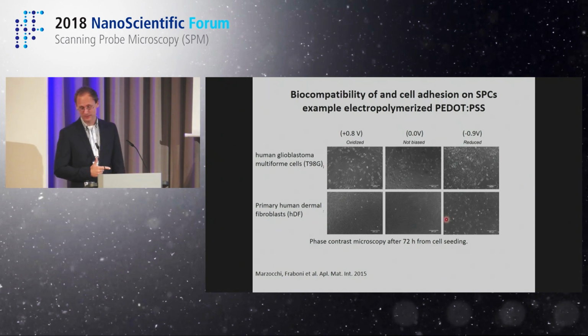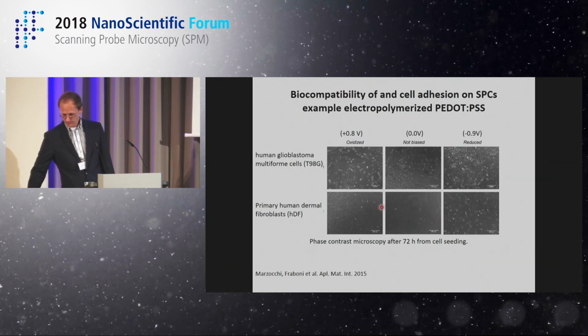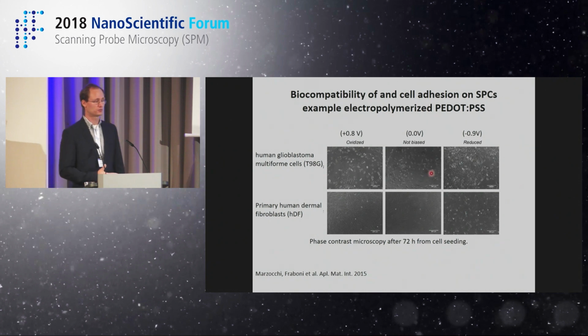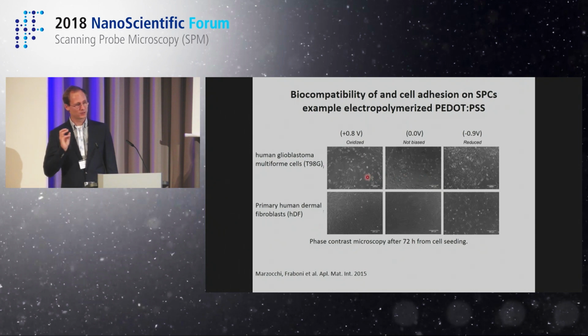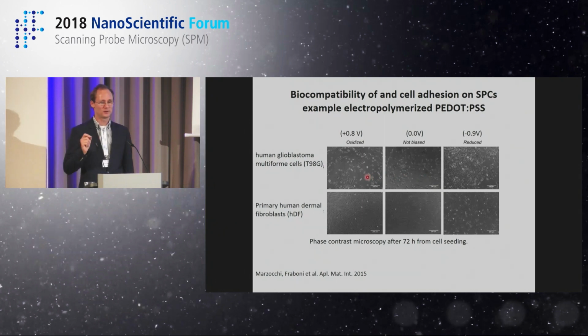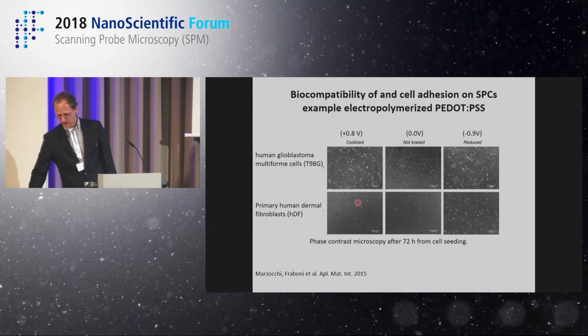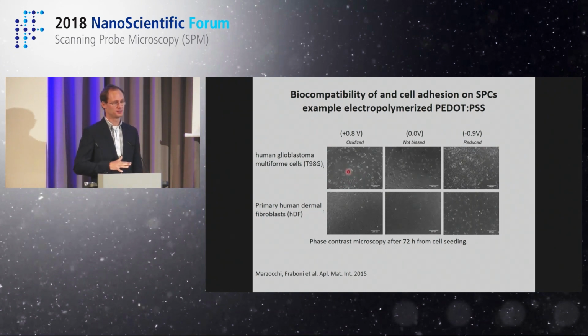The second reason is they are biocompatible. So you can grow cells on them. They are not toxic. It's a semiconductor that remains active without being toxic and without degrading. If you put silicon in water, it oxidizes, you have an oxide layer, and it's done. These materials here, in direct vicinity of water, of course, they maintain their electronic conductivity, and they are not toxic to cells. Even more interesting, the way cells grow on these materials depends, for example, on the amount of charges that are inside. So that's one of the first questions that we wanted to address.